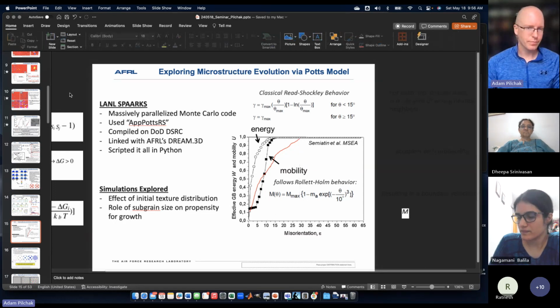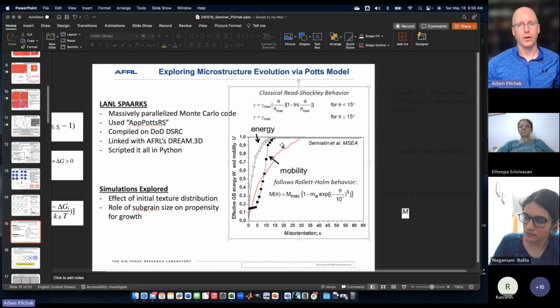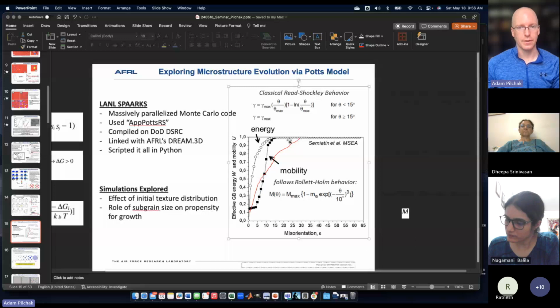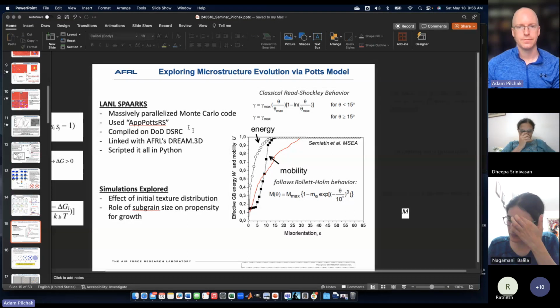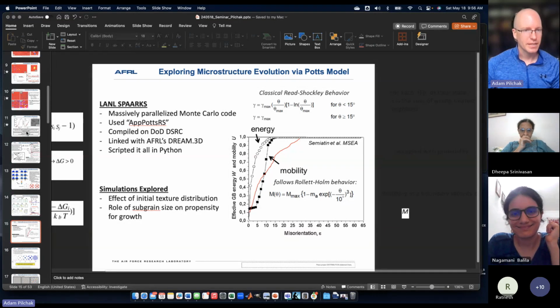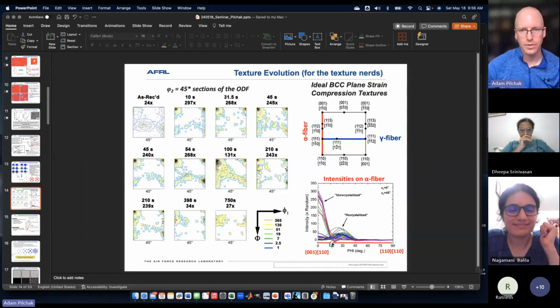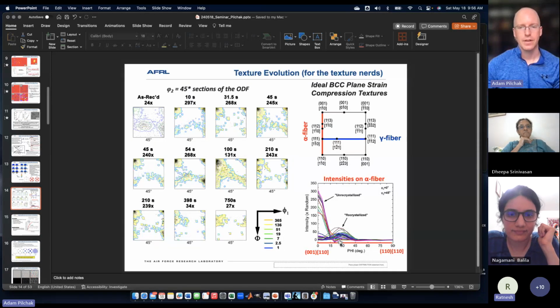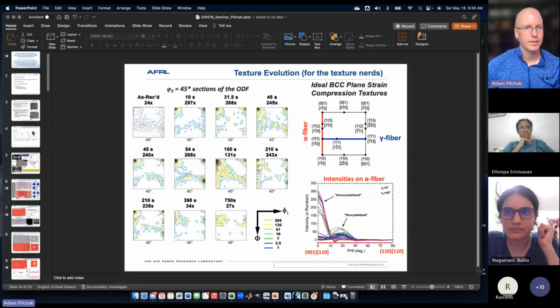And while we were working on this, there were groups at Manchester in the UK, and then in France as well. I forget the university, but they also made some nice observations. And the French group was also doing Monte Carlo modeling and ended up using something like around a 30-degree critical tolerance angle as well. And it makes sense with respect to where we're starting to see these big peaks of intensity in the recrystallized grains as well.